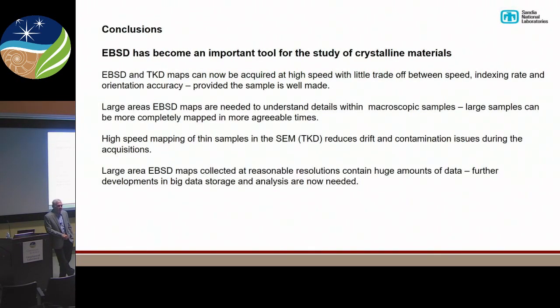Just a practical one. When you're looking at your thin samples, how thin do you have to be? Because with the 30 kV electrons, especially if you're doing it in transmission, you need to have fairly thin samples. Yeah, we try to make them about 100 nanometers or so. So it's a typical FIB sample, nothing